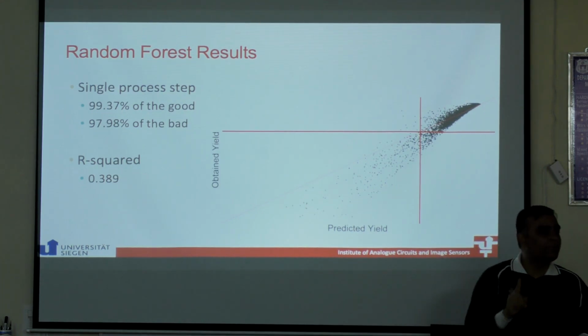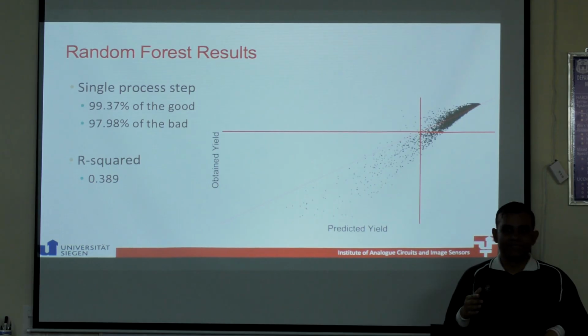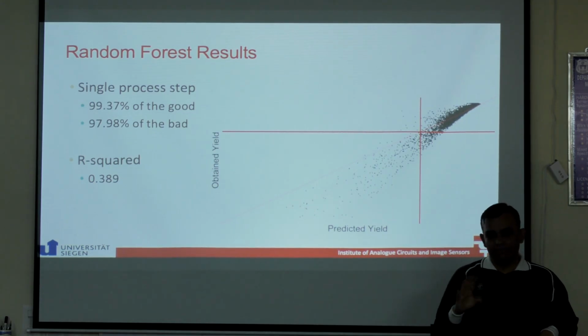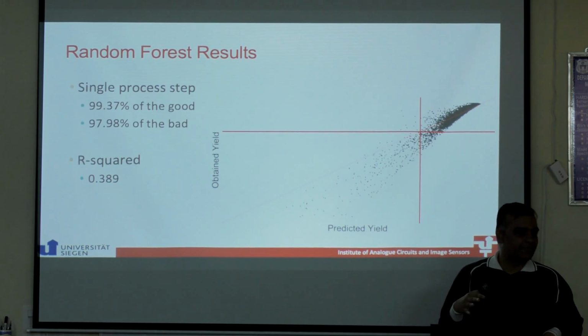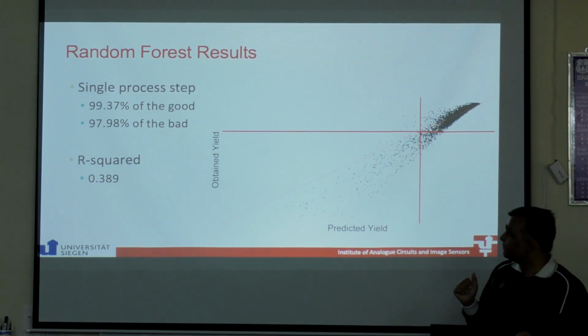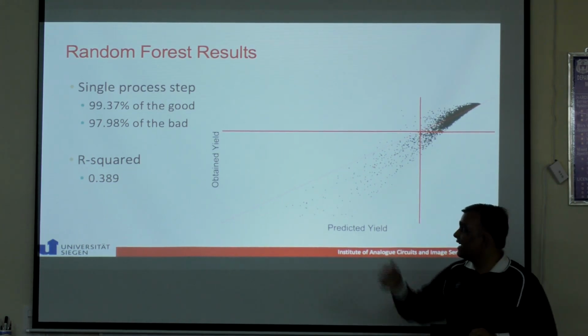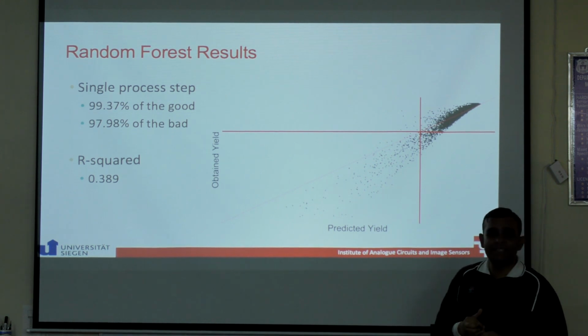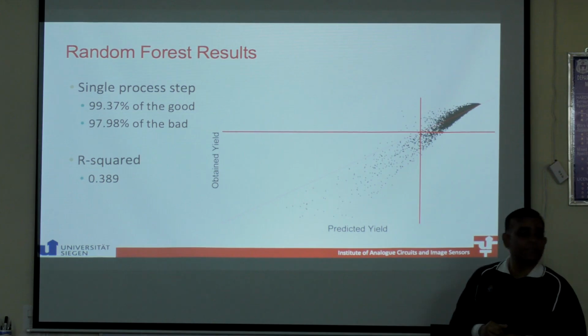This is after one process step, right? We were looking at a system with 4 processes, one after the other. So even after one process step, I can identify 99.37% of the good wafers and 97.98% of the bad wafers. These numbers look good, they are not good.